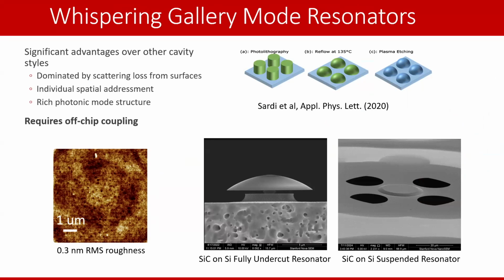So really, we mostly targeted this kind of suspended structure here, especially since if you wanted to do electro-optic tuning of your whole resonator, this is no good, because you would need to put the metal contacts in this region. But if you only care about tuning defects in a specific location on the resonator, which is another advantage of the whispering gallery resonator, as you have spatial addressing from the top, you could just put the contacts here and here and here and here, and then you have individual control.